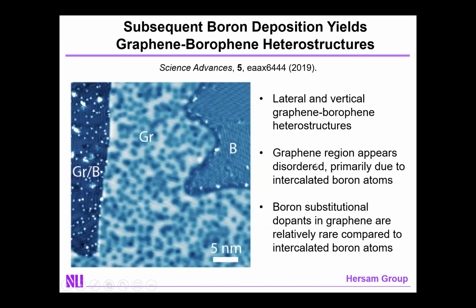This you can imagine nucleating either on the fresh silver if you originally had a submonolayer coverage of graphene. And if that were to occur, you can imagine that borophene growing until it hits the graphene and you form a lateral heterostructure in that case. You could also imagine the boron intercalating underneath graphene. And indeed, in this image here, you can see individual boron atoms intercalated underneath the graphene, and that perturbs the electronic structure of the overlaid graphene. And that's what these dark protrusions are on the graphene in this case.